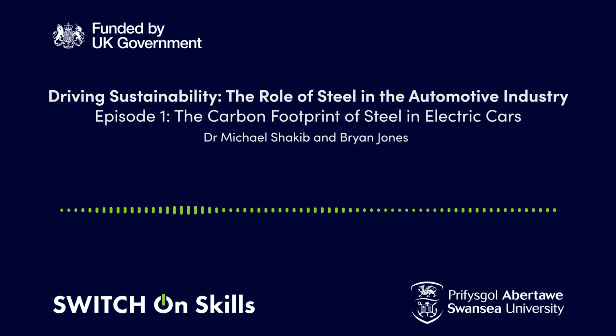So a car, after it's been assembled, is processed through a furnace to cure the paint at temperatures of 180 to 300 degrees centigrade, and with a bake hardening steel, you get a significant amount of precipitation of carbon and nitrogen, which significantly increases the yield strength of the material from a typical mild steel with a yield stress of, say, 180 megapascals up to 300 and even up to 350, maybe in the future 400 megapascals, as a consequence of that precipitation of carbon and nitrogen.